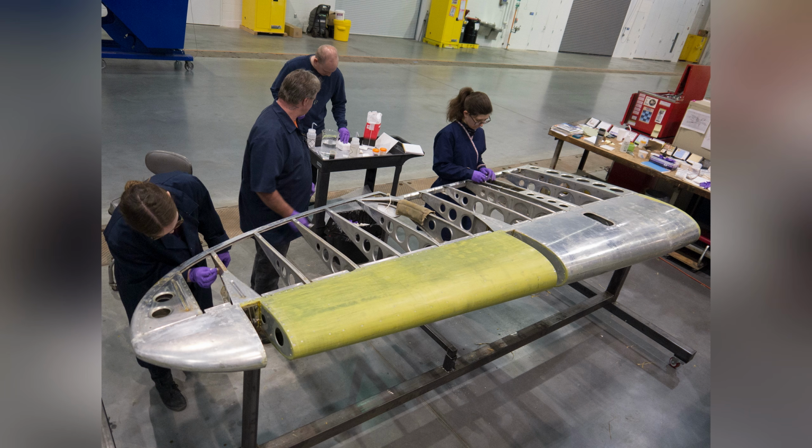Conservators faced a machine composed of overlapping materials, each degrading at different rates. The aluminum fuselage exhibits localized galvanic corrosion where dissimilar metals were joined in the field. The rivets holding the wartime patches have oxidized. The operational grime, composed of engine oil, hydraulic fluid, carbon exhaust, and dirt from unimproved European runways, has bonded directly to the exterior paint.